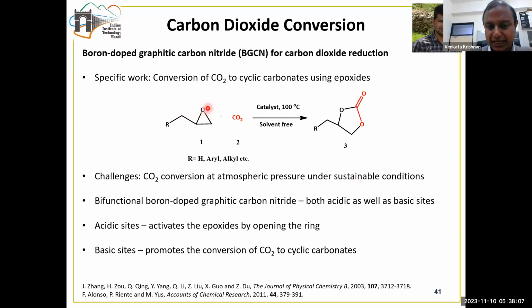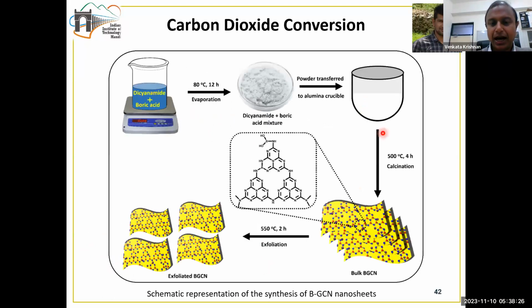This is that epoxide ring. This gets opened up due to the presence of the acidic sites which are in the catalyst. Subsequently, the carbon dioxide, which is an acid molecule by itself, adheres or adsorbs onto the basic sites which are present in the catalyst, and that leads to the promotion of this carbon dioxide to form the cyclic carbonates. And this is how we prepared this catalyst.